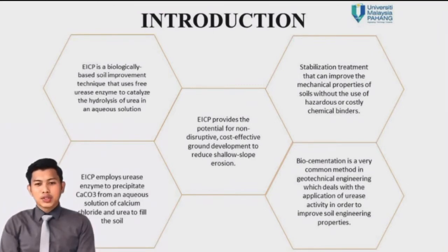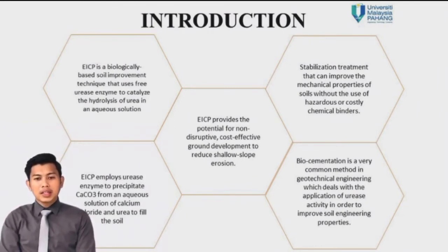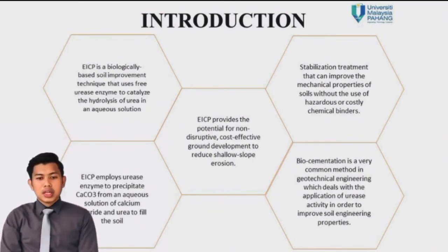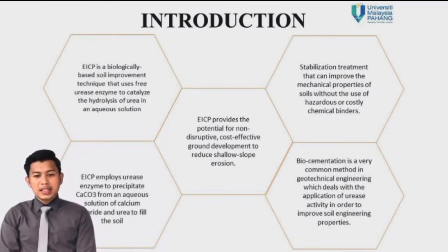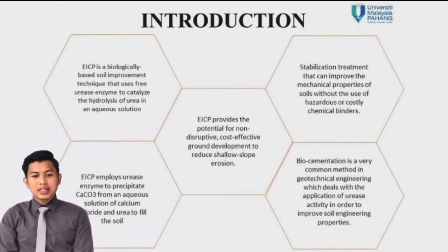EICP employs urease enzyme to precipitate calcium carbonate from an aqueous solution of calcium chloride and urea to fill the soil pores, reduce permeability and reduce compressibility, and cement soil particles to increase shear strength.